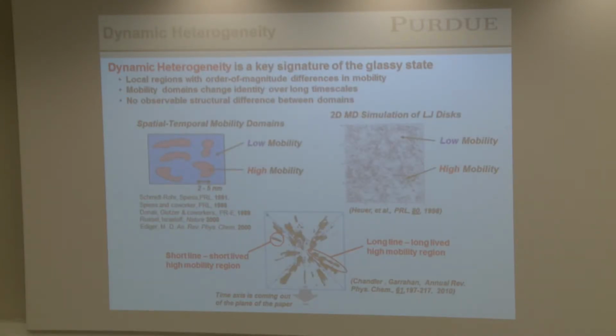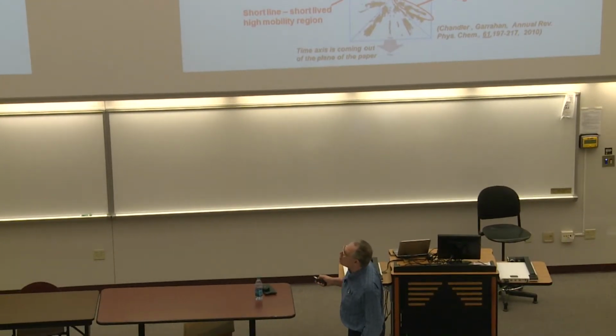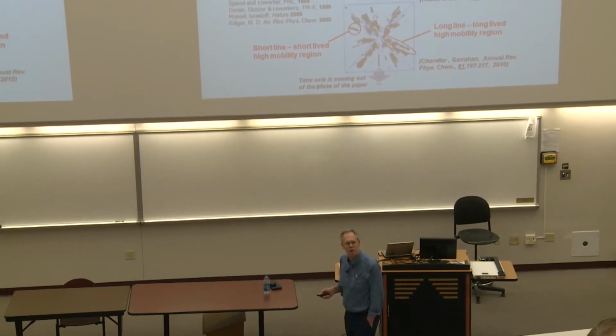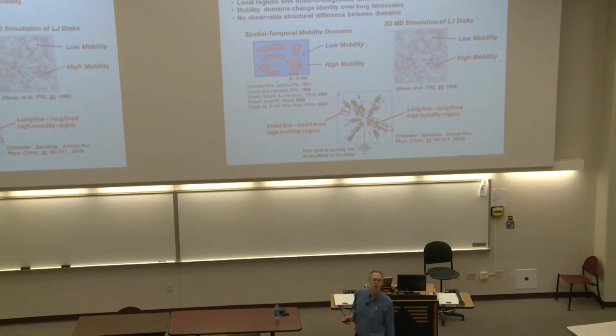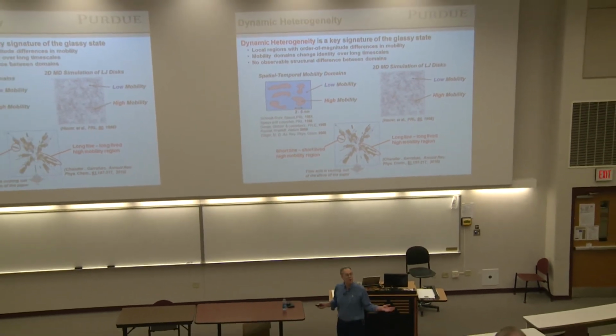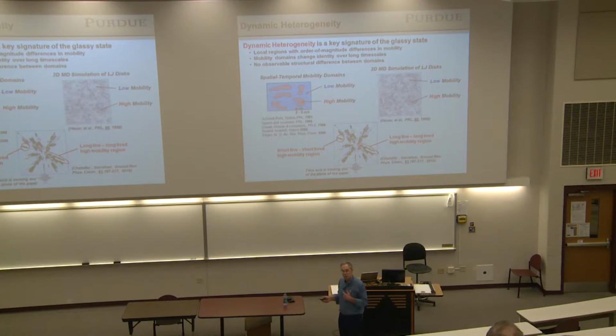Now, at the same time that was occurring, the glass physics community was having a major advance. And what one was finding out by a series of very clever experiments and molecular simulations is that the glass is an unusual state. It is heterogeneous, but only in the dynamic sense. If you look at a glass from a structural viewpoint, the glass looks spatially homogeneous. But if you look at dynamic probes on the nanoscale, you'll find regions that are low mobility, and you have other regions, nanoscale separated from that, that have mobility that is 1 to 2 orders of magnitude faster. So you have a heterogeneous material from a dynamic sense.